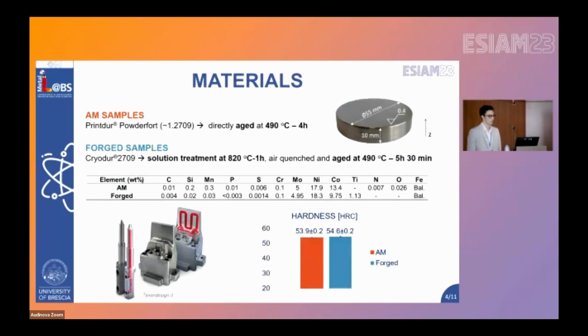In order to analyze material actually used for industrial components, we have selected the Prindur powder for the additive samples and the Cryodur 2709 as a reference for the forged sample. Actually, the Prindur powder was developed to generate components that in the end should have the same hardness, around 54 Rockwell, as the forged component. And since the aim of the development was this level of hardness, the chemical composition slightly differs from one to another, and so does the heat treatment.